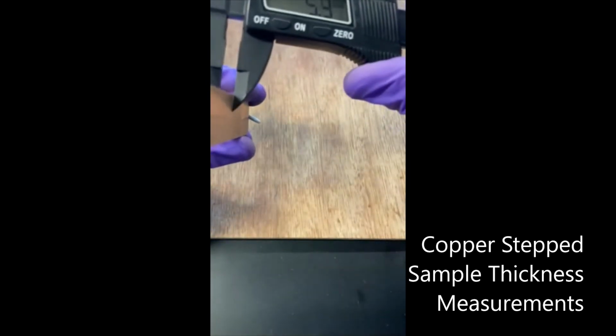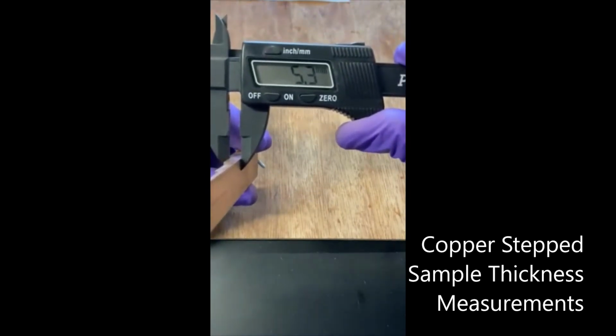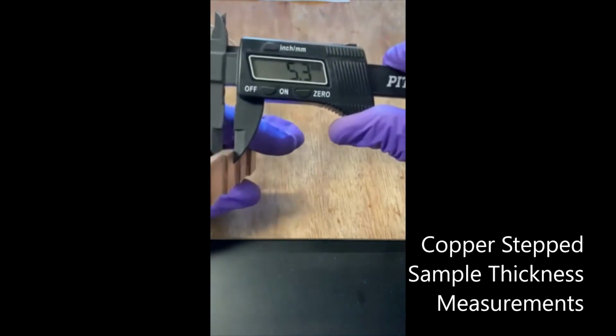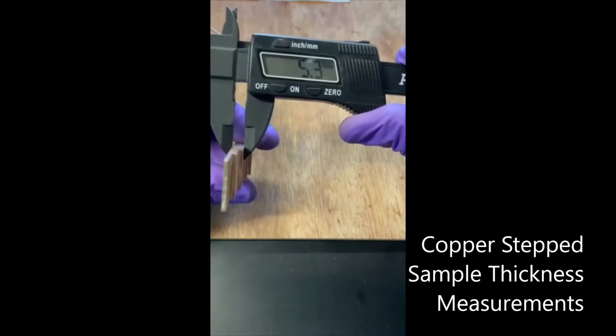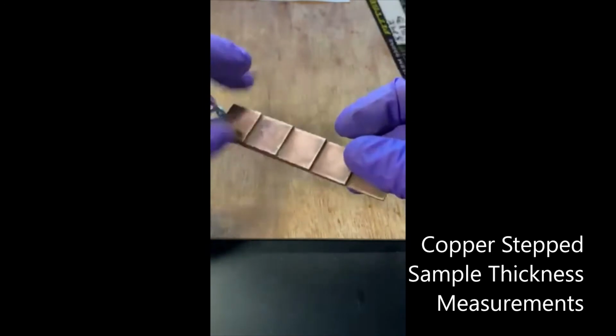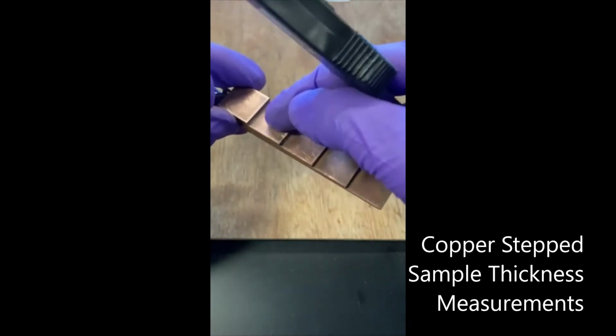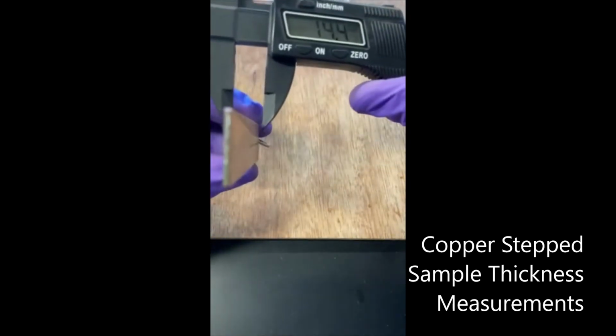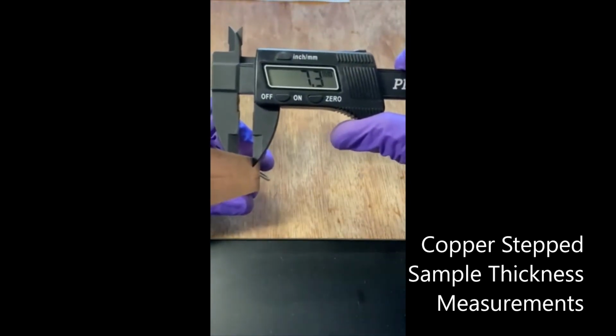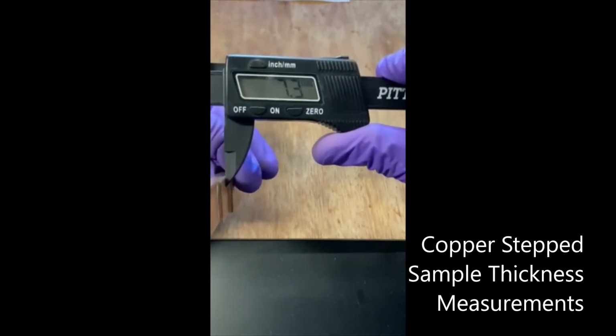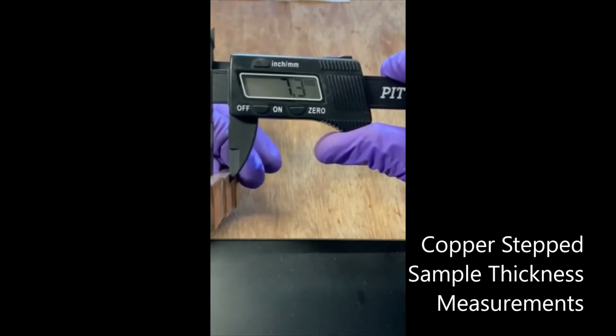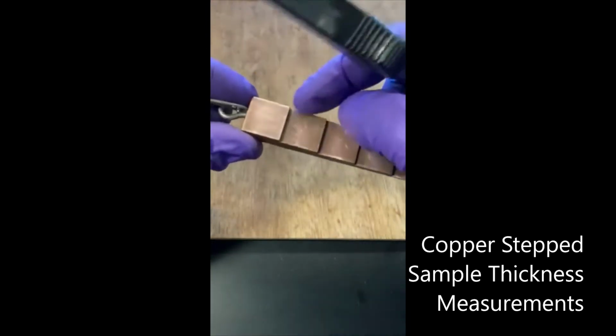Step 2 is roughly 3.3 millimeters. Step 3, the copper step number 3, is 5.3 millimeters. Copper step 4 is 7.3 millimeters, and copper step 5, the thickest step, has a thickness of 9.4 millimeters. Once again, this measurement process is repeated for the 3 other metal step samples included at the end of the video.